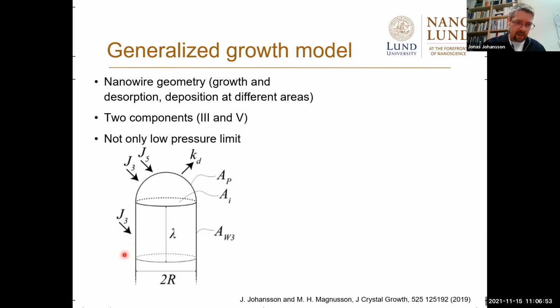So group 3 can deposit here and on the particle, and what is deposited here diffuses to the particle and can incorporate. Group 5 is only deposited here. That is the only contribution, and that can also desorb. And we have an incorporation area and an incorporation rate here at this interface. Since the particle is liquid, I treated diffusion through this liquid as fast. So this is not a nucleation limited model, it's just a mass transport model to understand the overall growth rate.